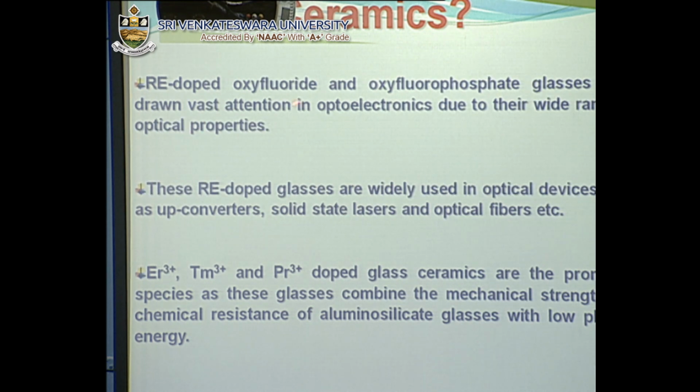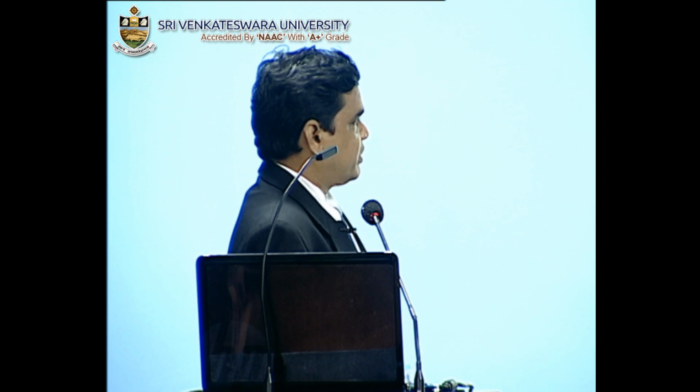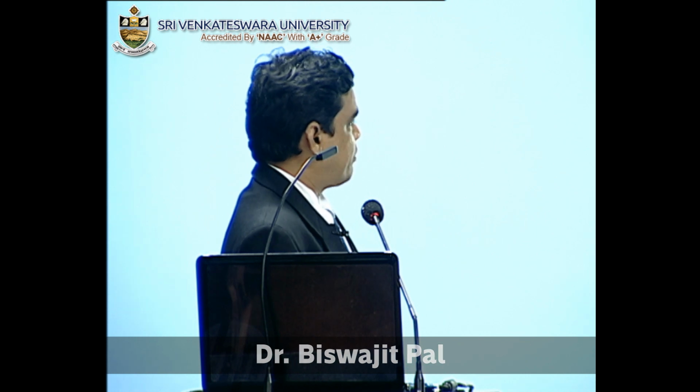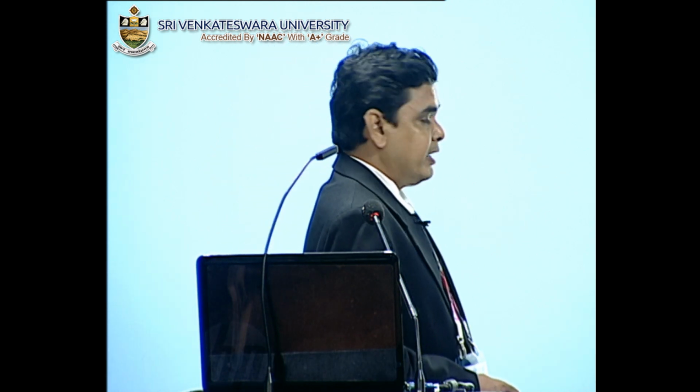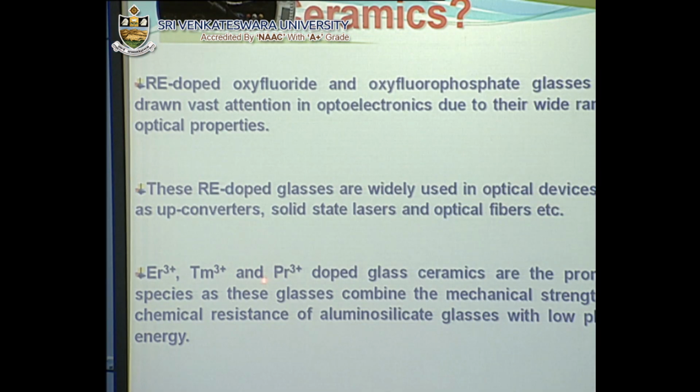Now, the rare earth doped oxyfluoride and oxyfluorophosphate glasses have drawn attention in optoelectronics due to their wide range of optical properties. These rare earth doped glasses are widely used in optical devices such as upconverters, solid state lasers, and optical fibers, etc. And among these rare earth elements, Er3+, thulium 3+, and praseodymium doped glass ceramics are promising species, as this glass combines the mechanical strength and chemical resistance of aluminosilicate glasses with low phonon energy.